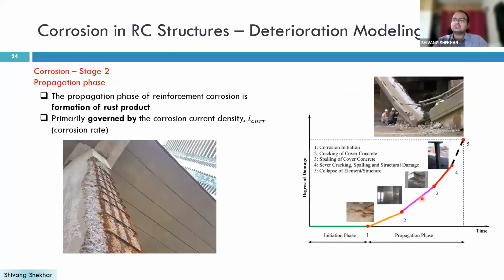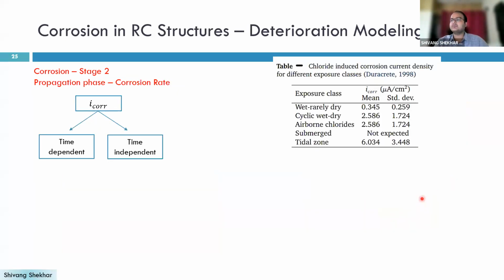The next stage is the corrosion propagation phase. Once the chloride ion diffuses and penetrates, the rust starts forming. The amount of rust that forms depends on the corrosion current density, or the corrosion rate. The higher the corrosion rate, the more the rust formation, or the higher the sectional area loss of the reinforced concrete member.